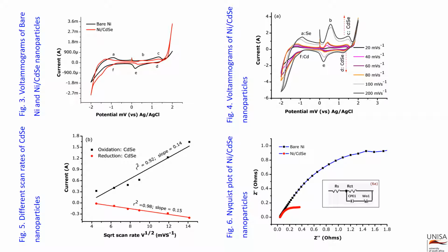The Nyquist plots were recorded at frequencies ranging from 100 Hz to 25 MHz and revealed the electrical properties of nickel-doped cadmium selenide, apparent from the semicircular and linear behavior of the system. Figure 6A was also used to simulate the specific parameters. The semicircular portion observed at higher frequency corresponds to the electron transfer limited process, whereas the linear part at the lower frequency range represents the diffusion limited electrochemical process, thus confirming a very fast electron transfer process. In this view, the observed results are in accord with the Nyquist theory.